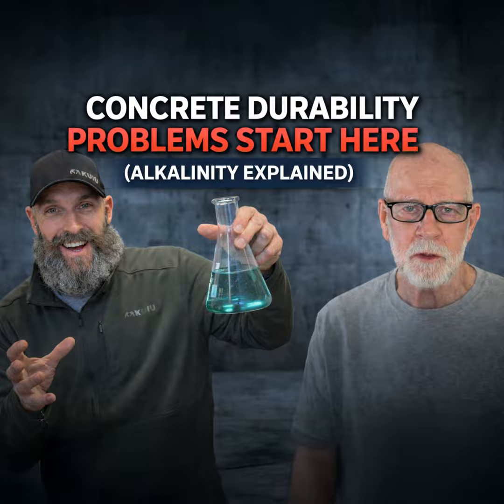So when I looked at the study conducted by ACI with all these different inputs from the 1940s through around 2005, it showed that the higher the temperature, the better the compressive value was at 28 days, but the weaker the concrete was at 365 days. Right. That correlated with what we're seeing with alkalinity. Because if you add everything else in, the only thing that makes sense is alkalinity.